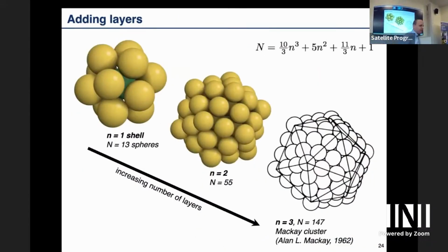And then when you have these icosahedral clusters, you can do something that goes back to another crystallographer, Alan Mackay, in 1962. He said you can add shells. You can start with a single icosahedron. Here's a triangle. On top of the triangle, you can add a bigger triangle. You see a bigger triangle made from 6 spheres. Here it's just 3 spheres. And then you can go to 10 spheres. And you can grow this shell by shell, layer by layer outwards.